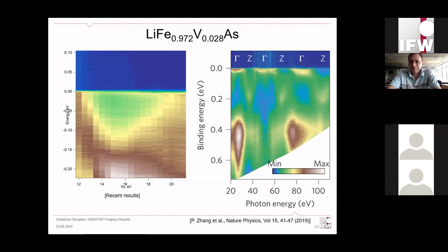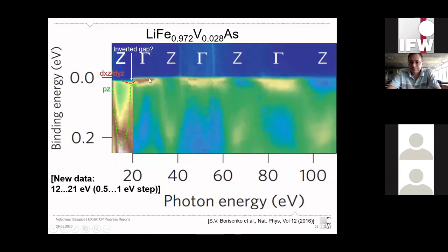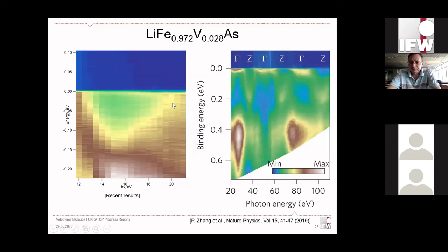Indeed, if you look closely at this detailed map, it looks logical that if we shift it slightly higher, the inverted gap should be somewhere here, because when we map along Z like this, that is where it is expected. This is the Z direction. In the perpendicular spectrum you clearly see all this crossing, and I see no reason why the surface topological spectrum should not be visible when we approach it. It should be sharp and visible, the more vanadium controls it.